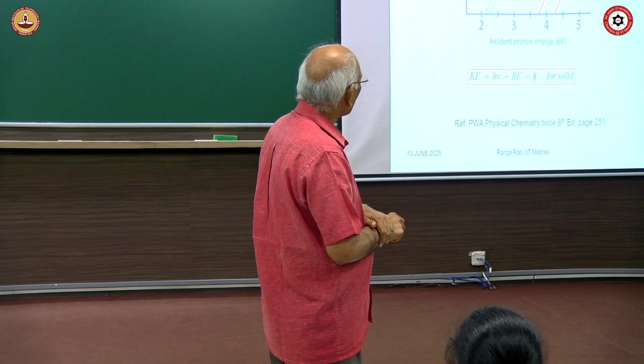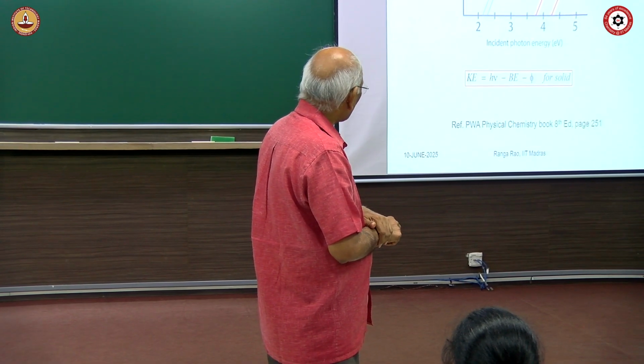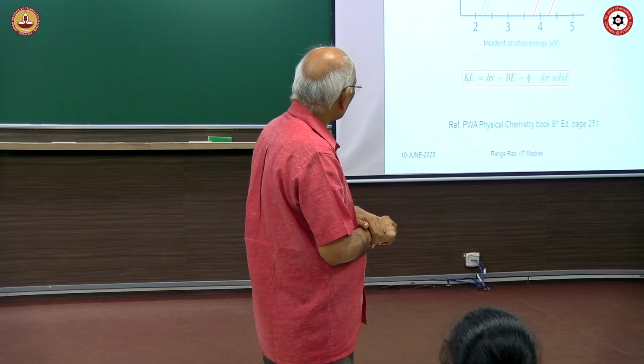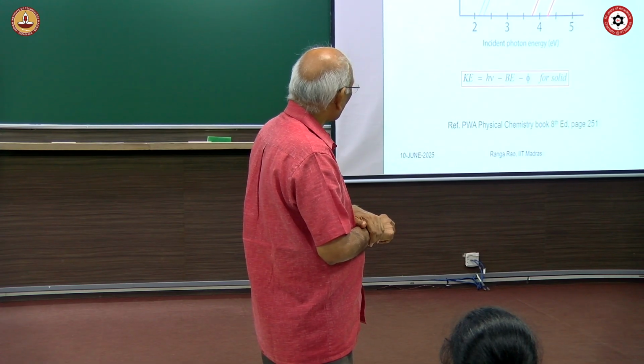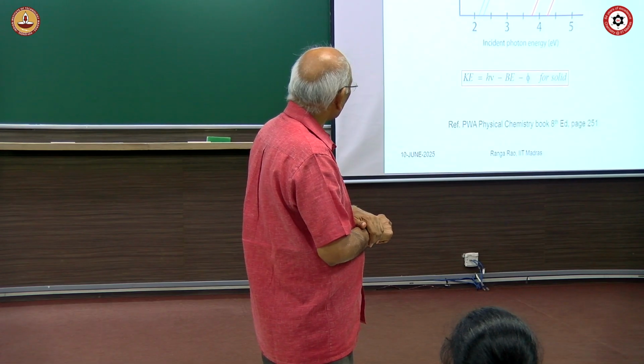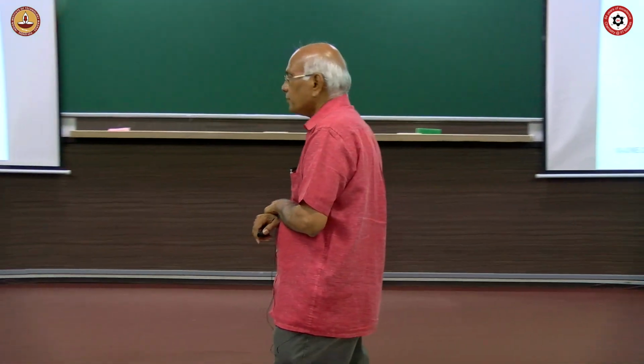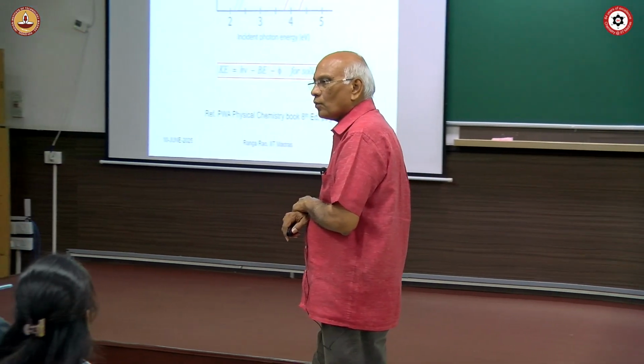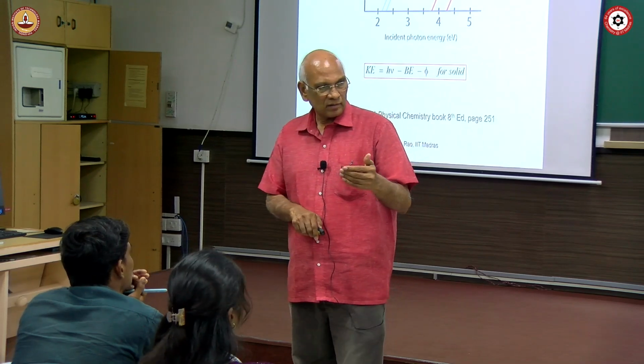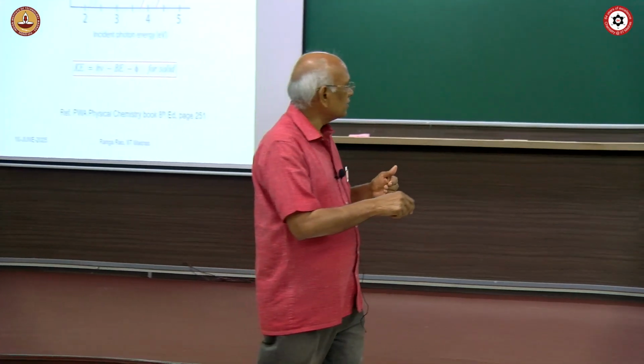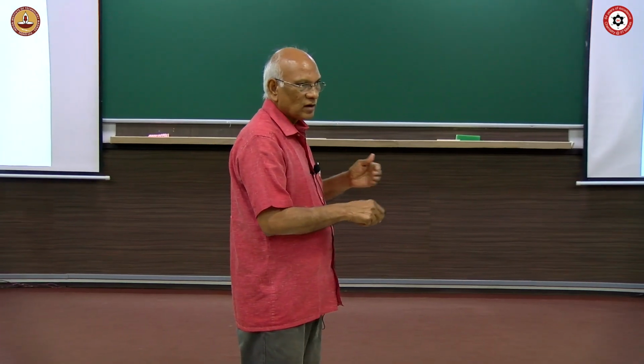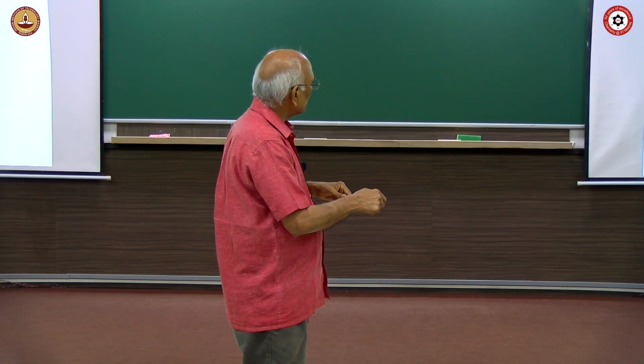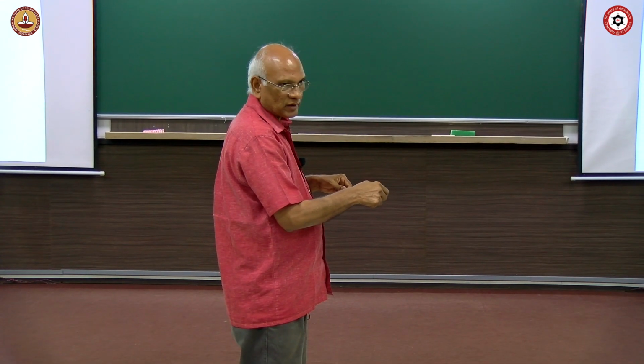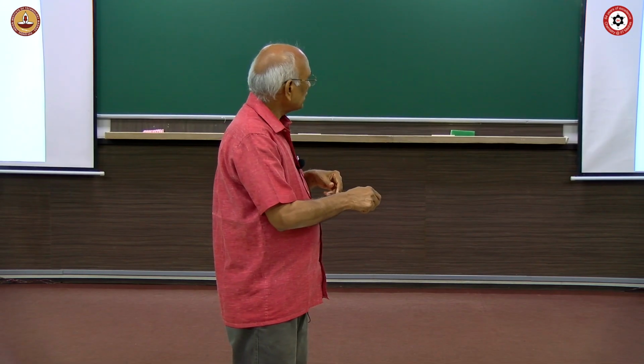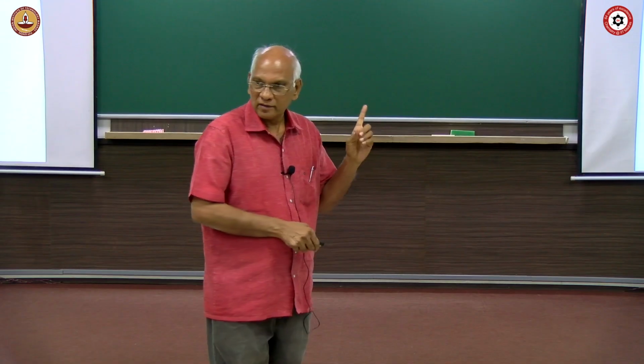Right. For example, if you take these 4, for silver, the incident photon energy is somewhere around 4 here, much higher than magnesium or lithium or potassium. It means the work function is very high. That's the reason why you need a higher photon energy to get electrons out. If you use any of these lower photon energies, you will not be able to ionize any electron from silver. So that is the threshold frequency required.